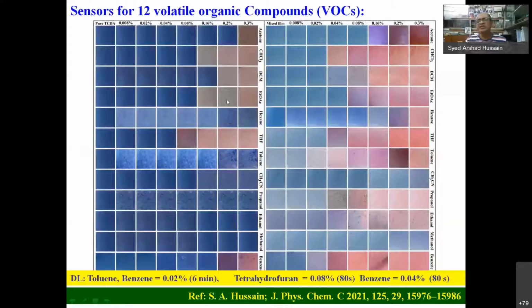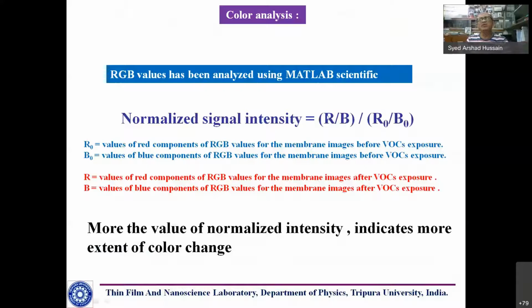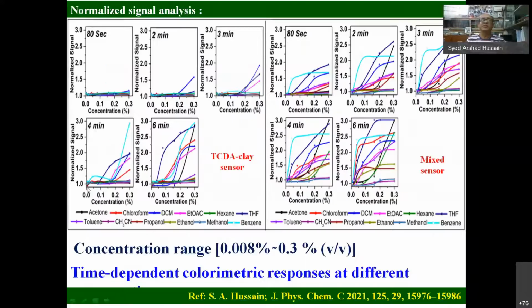But you see the extent of color change is different. Although one can have a sensation of response, it's difficult to quantify. To do that, what we did, using a simple MATLAB program, we recorded the RGB value from the photographic image of these colors. Okay, and then we analyzed the normalized signal intensity, which is red versus blue divided by R0 B0, where R0 B0 is the component of red and blue before the exposure, and R and B is after the exposure. So if the normalized signal intensity is increasing, that means your extent of polymerization from blue to red is higher. So in this way, one can quantify, and you can see we have plotted this normalized value with different concentrations, and you can see it's so linear. So one can have a good idea of quantification for the sensors.